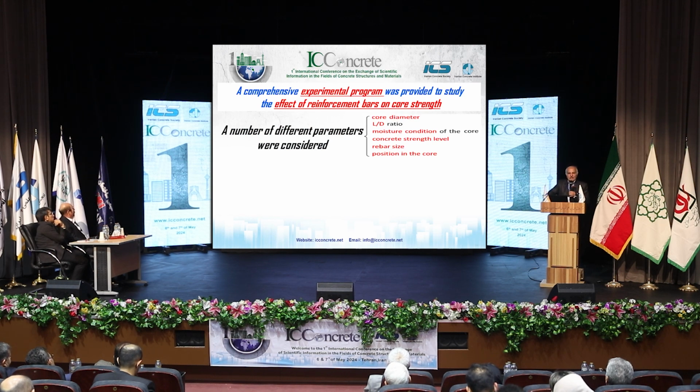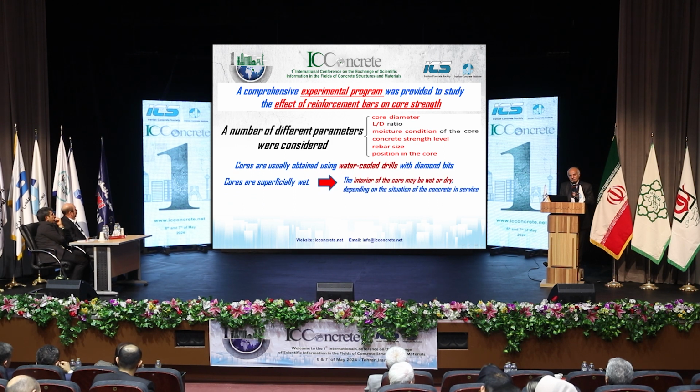So we took a comprehensive experimental program to see the effect of the reinforcement on the core strength. We considered a number of parameters. We have listed here core diameter, L/D ratio, moisture condition of the core, concrete strength level, rebar size, and the position in the core.